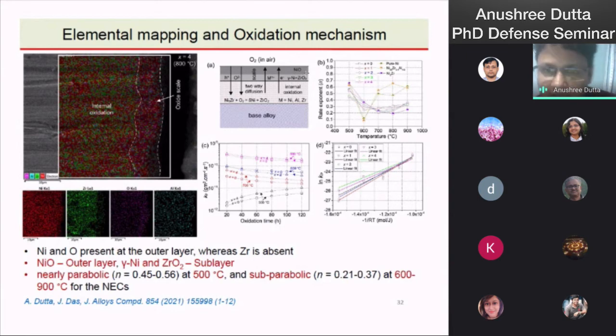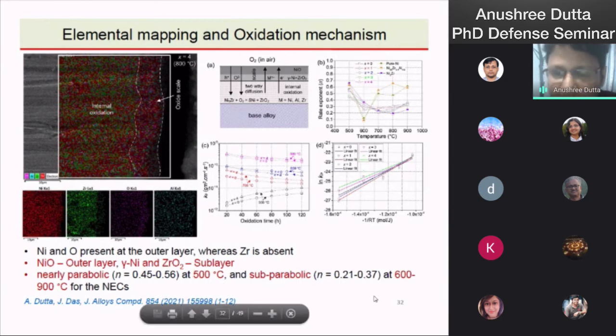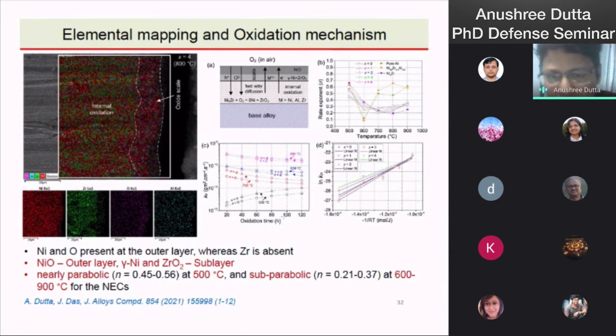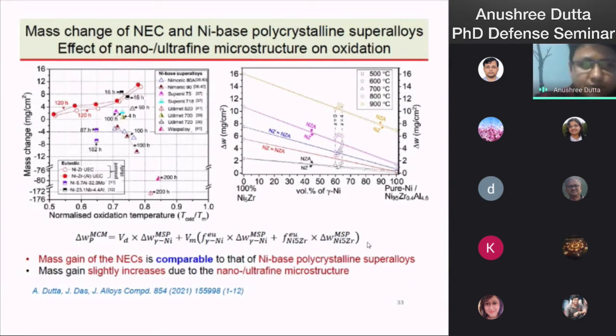the NiO scale. And the rate exponent shows that the oxidation of the NECs exhibited nearly parabolic behavior at 500 degrees centigrade with rate exponent 0.45 to 0.56, whereas subparabolic with rate exponent 0.21 to 0.37. And their parabolic rate constant is estimated with oxidation time. The mass change of the NECs is compared with the other nickel-based polycrystalline superalloys.